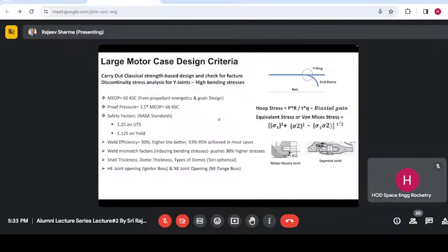And this has to be experimentally determined, but theoretically the gain is up to 15%, and you can actually derive it. And I had actually derived that formula just because I wanted to be very clear that what I'm doing is correct. But we used 12% at that time as biaxial gain, and that gave you some benefits on the allowable strength of the material.